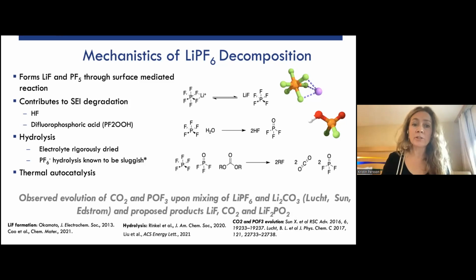There's been hypothesis about hydrolysis or thermal autocatalysis. In order for us to add PF6 or PF5 to our reaction network, I have to have some idea of how it decomposes. And we were unable to find it to begin with. We found some really nice suggestions in the literature, both by Lucht and by Sun and by Edstrom, that if you mix lithium PF6 with lithium carbonate, there should be an evolution of lithium fluoride, carbon dioxide, and lithium difluorophosphates and those kinds of things. But again, these are suggestions and shown by Lucht that they've seen evolution of these gases and species, but not really the mechanistic reaction behind it.